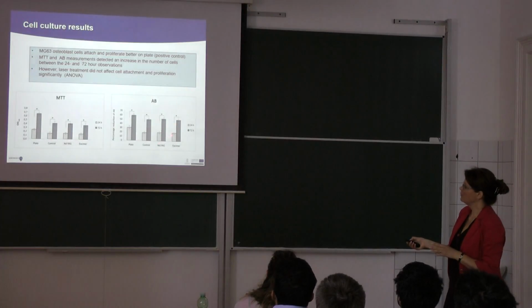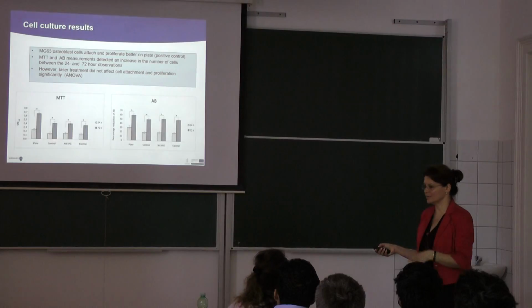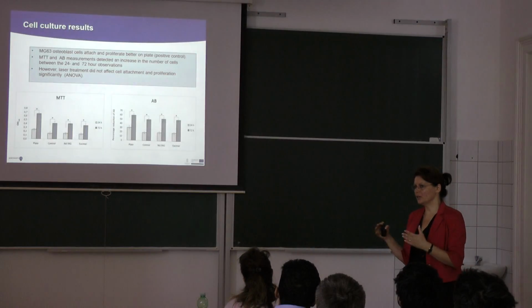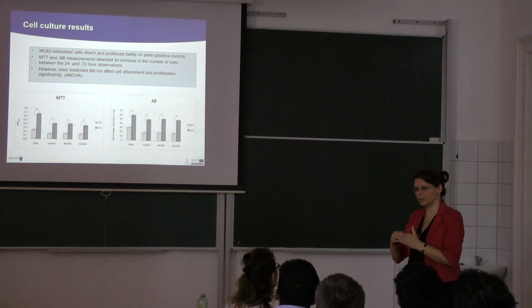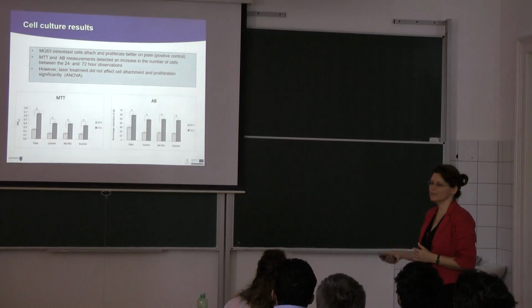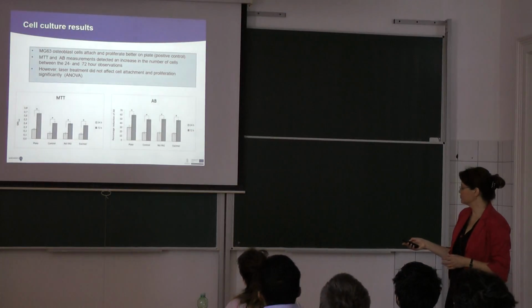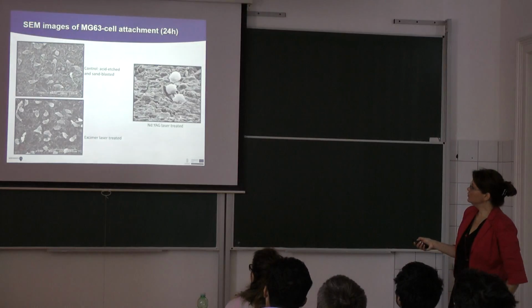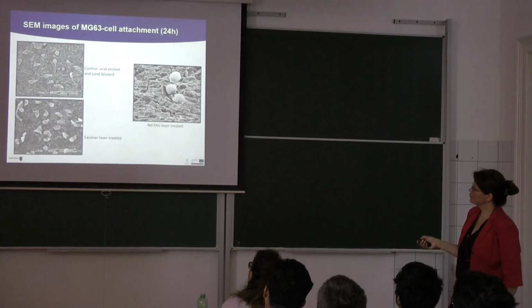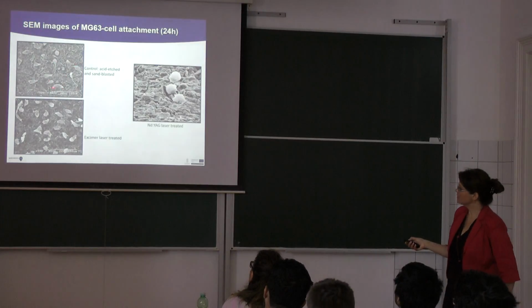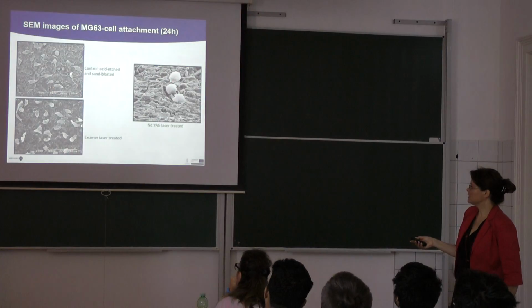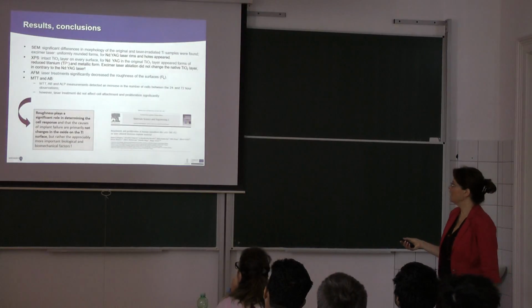let's say, surfaces, but really it did not affect the cell attachment well. We assume that because the roughness was changed in a not good manner, this is why it happened like that. Then we made some scanning electron microscopic images of the MG63 cells, as you can see here. We could not establish any difference between them.